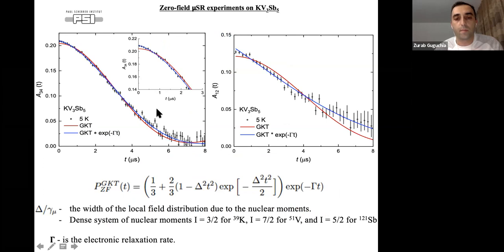Here I want to highlight one thing: in this system we have a large, dense system of nuclear moments, with large nuclear moments and high natural abundance. So in that case we expect the relaxation rate to have the form of the so-called Gaussian Kubo-Toyabe function, which reflects the field distribution at the muon site created by the nuclear moments. But you can clearly see that the red curve, which is a Gaussian Kubo-Toyabe function, does not fit the data well,